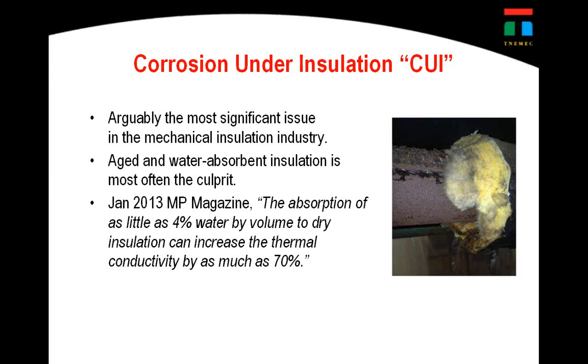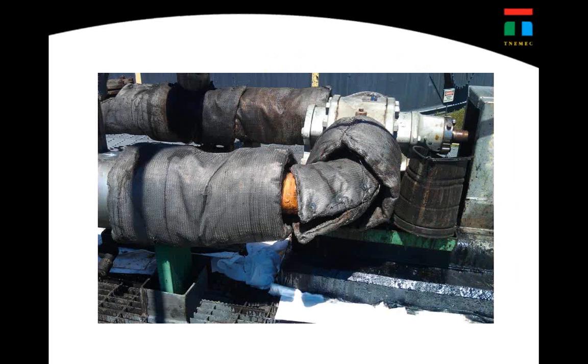NACE's Materials Performance Magazine, which is the basic magazine for the National Association of Corrosion Engineers, came out with a piece which I think is interesting and worth noting. The absorption of 4% water by volume into dry insulation can increase the thermal conductivity as much as 70%. So when you have those kinds of numbers, just a little bit of moisture can make that a huge problem. So we think that there are advantages to looking at a directly applied solution. If this were a very typical power plant or a refining operation or even a mechanical space in a building where you have insulation, any place you have an air gap, you're going to have CUI issues.